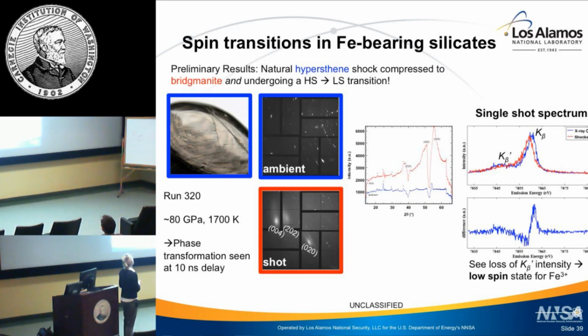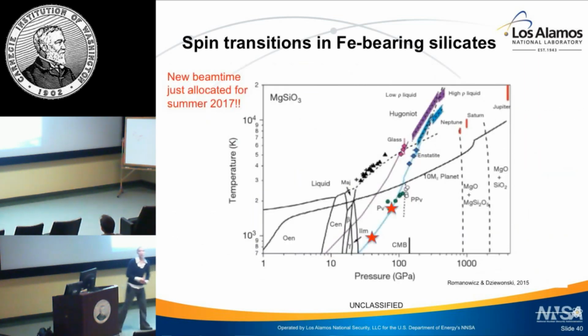Just to give you an idea, I know this is the magnesium end member, but of where we are on the Hugoniot, we were somewhere around 40 or so GPa, and then a little bit higher, approaching a megabar. Finally, the ability to use X-ray spectroscopy technique in an ultra-fast setting to explore differences in electronic versus structural transitions.